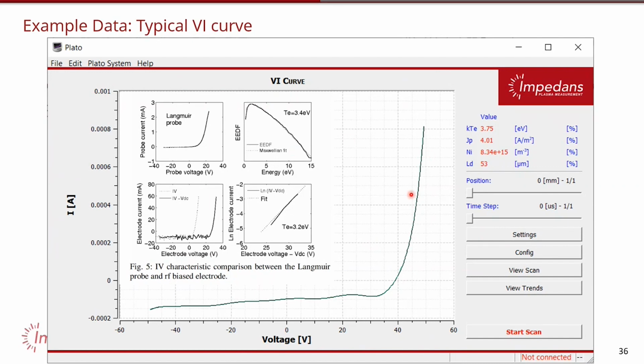And what's extra nice about this technique is that a Langmuir probe is what's called a DC probe, so you need to have a conductor in the plasma and so on. With this method, because it's an AC probe, if you're depositing materials, you can measure these plasma parameters through the deposition, because that's just a capacitor, and a capacitor is a short to AC. So that means you could have a chamber where you're depositing and etching and making the chamber very messy, but be getting real-time plasma density and electron temperature measurements from your powered electrode, okay?